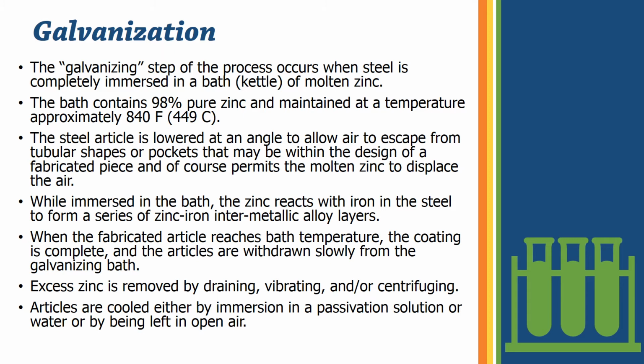While immersed in the bath, the zinc reacts with iron in the steel to form a series of zinc iron intermetallic alloy layers. When the fabricated article reaches bath temperature, the coating is complete and the articles are withdrawn slowly from the galvanizing bath. Excess zinc is removed by draining, vibrating and or centrifuging.